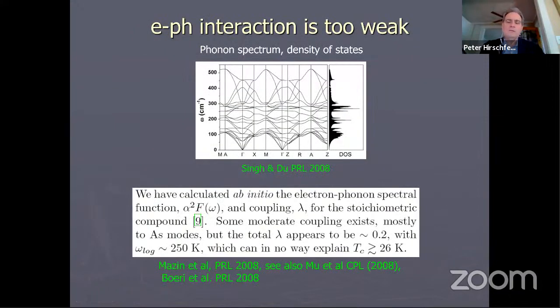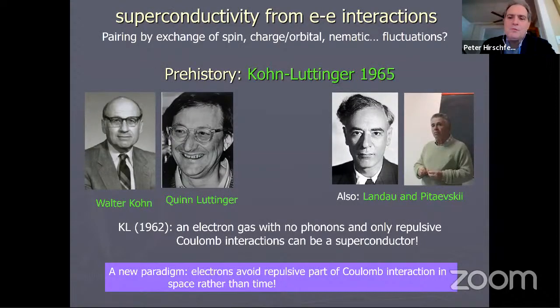Okay, now, why do we think electron-electron interactions are responsible for superconductivity and not electron-phonon? Well, by 2008, ab initio calculations for electron-phonon interactions and the calculation of the so-called Eliashberg spectral function, alpha squared F, were pretty accurate. And the initial calculations for these materials showed that the total dimensionless coupling lambda was about 0.2, which could not give you anywhere close to the observed critical temperature of 26 Kelvin. So that's fine.